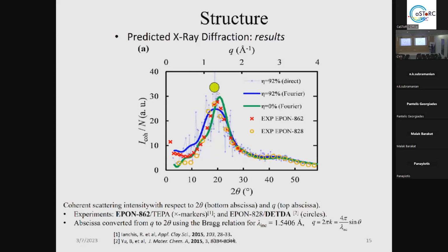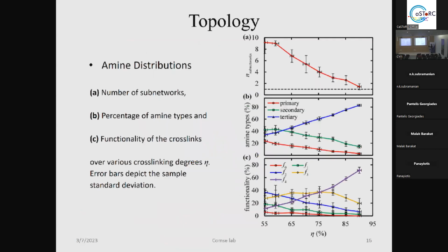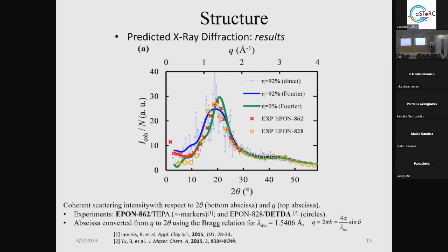We can see also here the difference between the uncross-linked, which is the green line. It has a sharper curve here around the 1.2 Q space, which is about 5 angstrom, compared to the shorter and wider bold blue line, which is the glass system, due to the fully glassy system. And because we have a fully glassy system, we have broader distances through the network. And that's why here you can see the wider and shorter XRD.